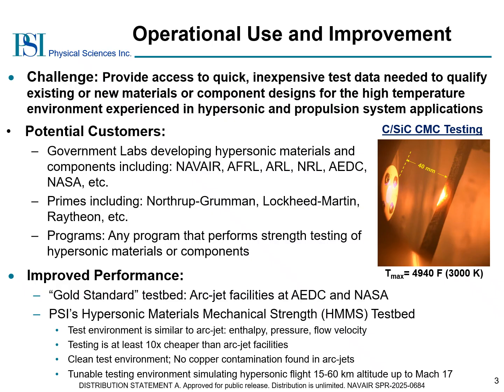The source of the high enthalpy flow in the PSI testbed is PSI's patented microwave-driven jet, or midjet, technology. The midjet is a microwave torch that generates high enthalpy flow through expansion of a high pressure plasma formed in an electrodeless discharge in the torch plenum. As a result of utilizing an electrodeless discharge to produce the high enthalpy flow, the midjet produces a clean test environment without any of the copper contamination that results from electrode spallation in ArcJet.